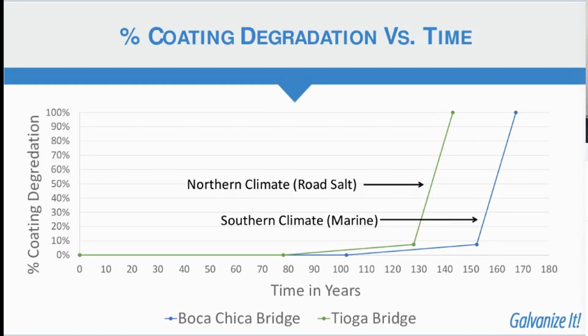Once that chloride threshold is exceeded, the model shows that the zinc coating will corrode at a rate of approximately 3 microns per year. But that depends on the amount of moisture in the concrete. It depends on the wet and dry cycles, cracks in the concrete cover, use of concrete additives, and other factors.